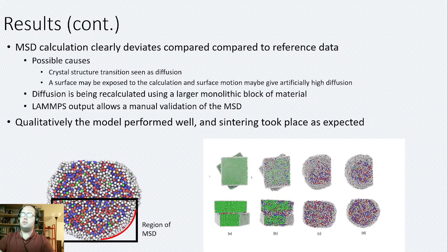And so on the first one, it's because there's an exposed surface, and so it's not really tied to a crystal structure. But as it shifted through this crystal structure, it caused motion, and because the MSD is only looking at a position change, it doesn't really check for the center. It's picking that up as diffusion, which is not really diffusing. The crystal structure is just opening up.